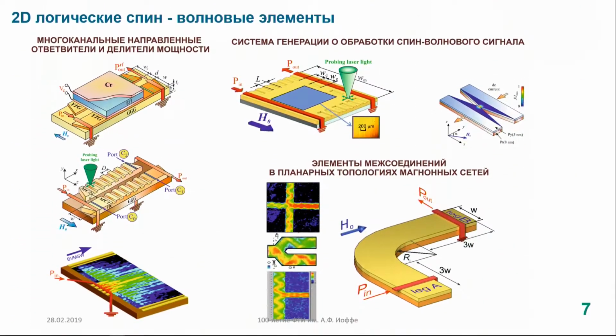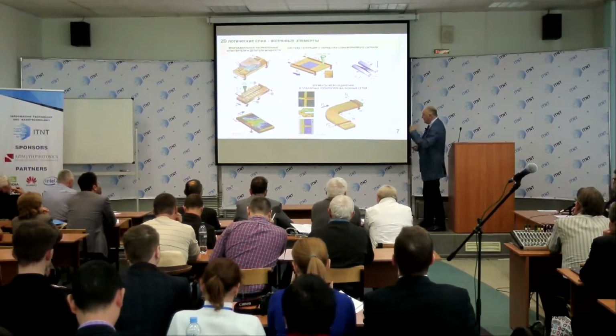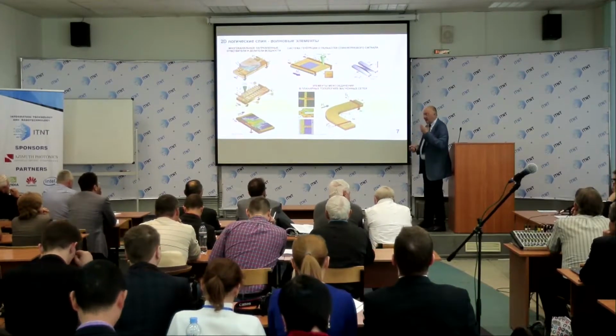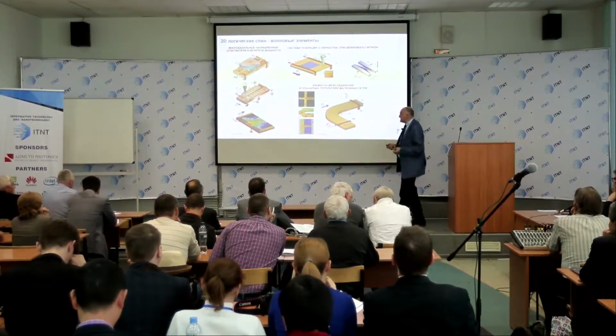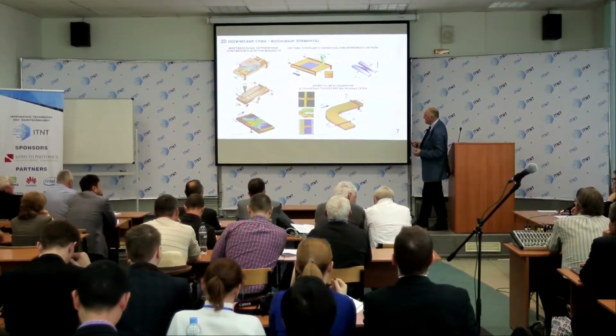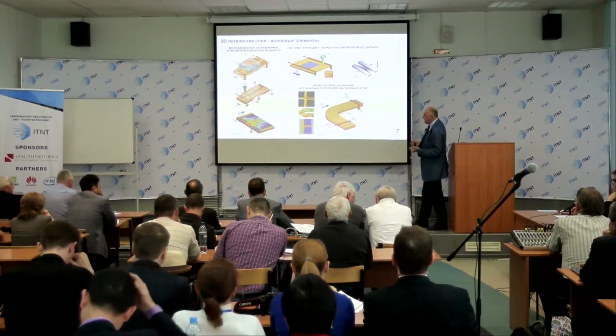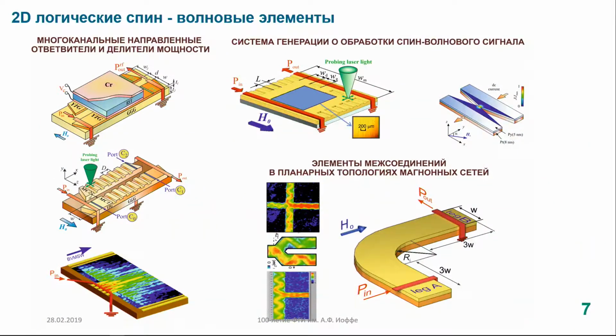For example, these Brillouin light scattering experiments show that, really, if we excite a wave in one direction, which is the typical shape as shown in the previous case, it can propagate in one part of the structure and cannot propagate in another part of the structure. The red color shows that the intensity is really big. Or, for example, you can make a cross-section element where you excite the wave and the wave will propagate in this direction, or in this direction, but will not propagate in the further direction. So you can make a connection even in the form of a right angle.